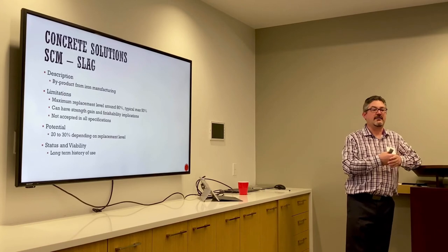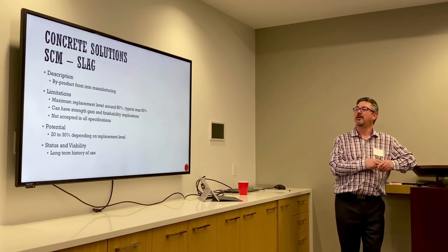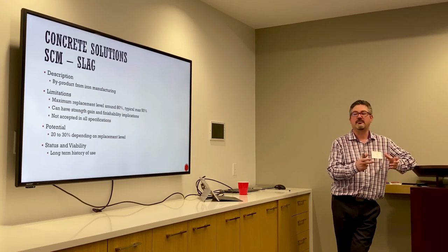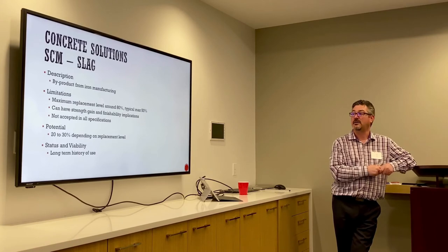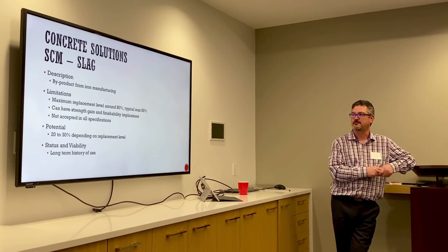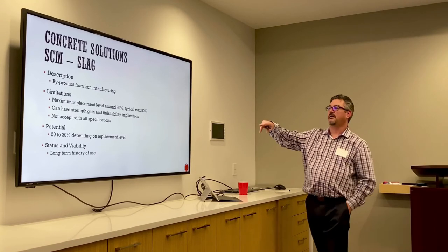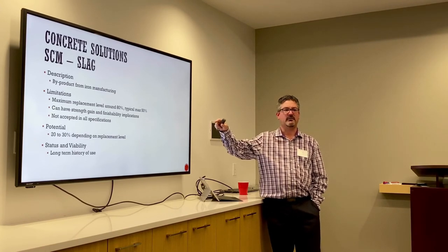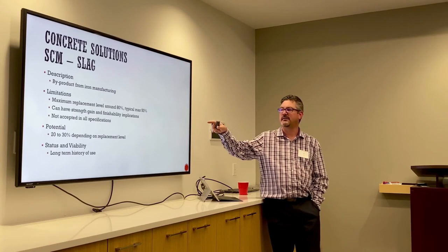Slag. This is from iron manufacturing. So it's a byproduct of iron manufacturing. It's a waste material from iron manufacturing, but it's not waste if you don't waste it. So it's used in cement and concrete production. Much higher replacement levels, typically around 80% maximum, but typically used around 50%.